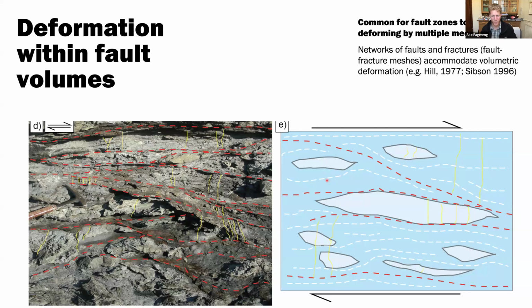You can do it by networks of meshes of shear and extensional fractures, or by a combination of those two things, so that the competition between different strengths doesn't just set what the bulk strength is, but also what the bulk mechanism is, though not necessarily excluding other mechanisms. So in this case, you have frictional sliding on clay-rich surfaces, which could be velocity weakening or strengthening depending on conditions. You have a lot of dilatancy related to tensile cracks, and a lot of local, very small-scale diffusion driving the overall flow of the matrix.